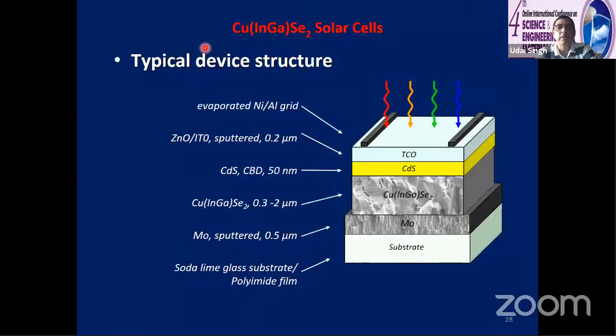So if you see the typical device structure for the copper indium gallium diselenide, you start with a substrate, which can be a glass substrate or the polyimide if you want to have a flexible one. And then for back contact, one uses the molybdenum, which is the standard. And then you have the copper indium gallium diselenide, which is referred to as the absorber layer. It's a p-type material. Then you have to make a PN junction.